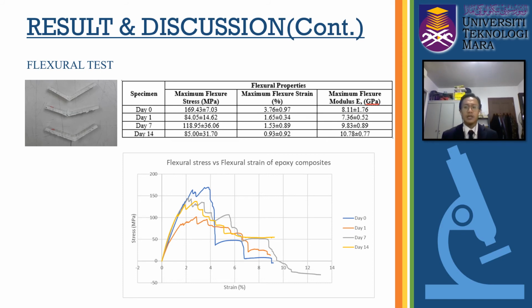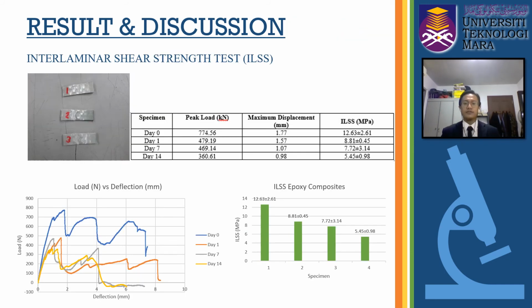From this test, it can be accepted that 1 day of submerge has the lowest flexural modulus because it has lower absorption of distilled water compared to 7 days and 14 days. The ILSS test is to investigate the shear strength of the epoxy composite.